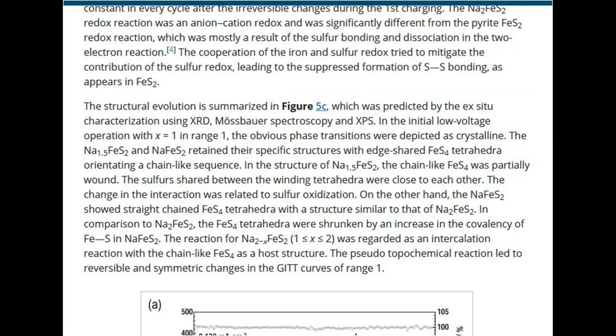For the cooperation of the iron and sulfur redox, the iron redox tried to mitigate the contribution of the sulfur redox, leading to the suppressed formation of S-S bonding, as appears in FeS2. The structural evolution is summarized in Figure 5c, which was predicted by the ex situ characterization using XRD, Mossbauer spectroscopy and XPS. In the initial low-voltage operation with x equal to 1 in range 1, the obvious phase transitions were depicted